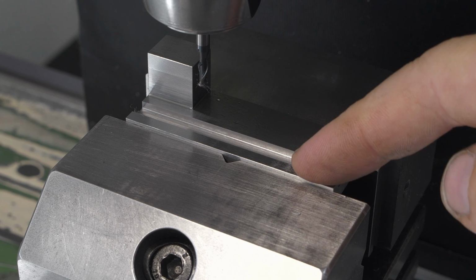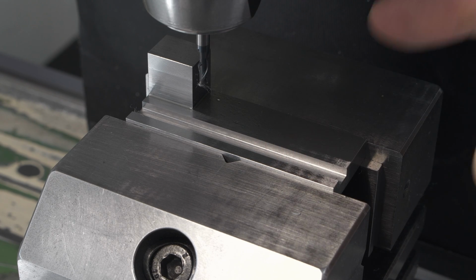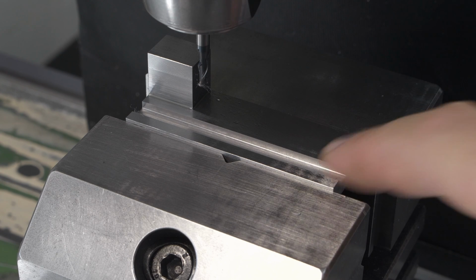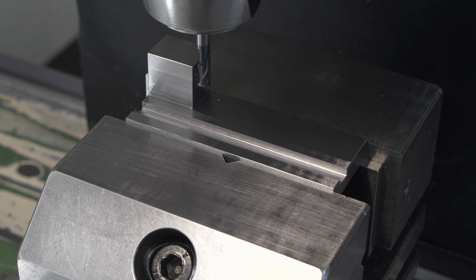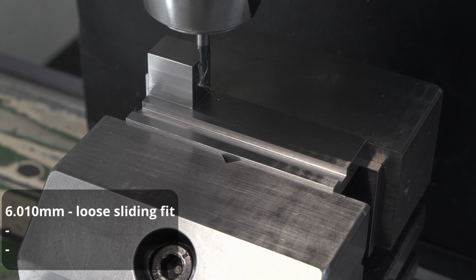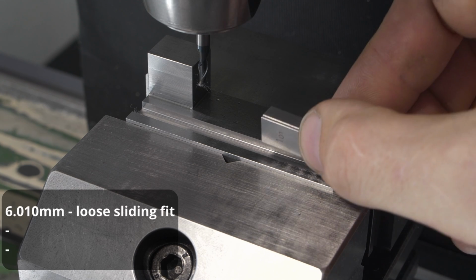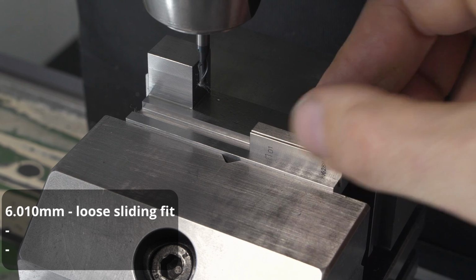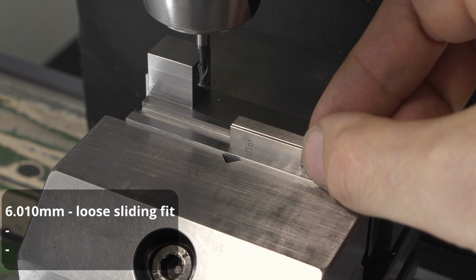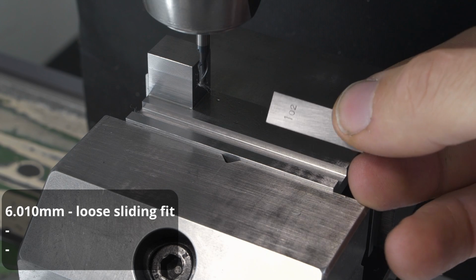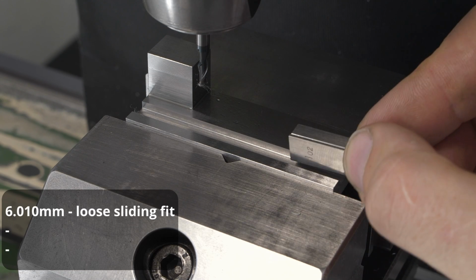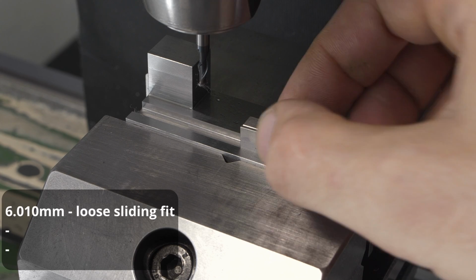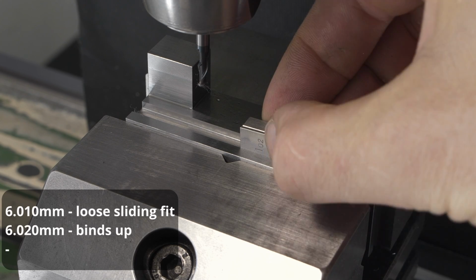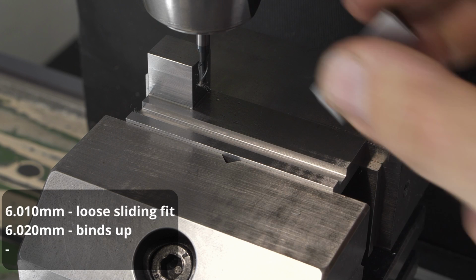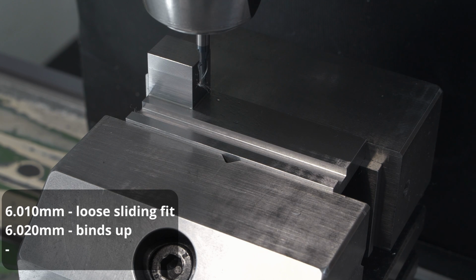I cut the slot in the part using a 4mm end mill, and I finished it to a size. So a 6.01mm gauge block with a nice loose sliding fit in there, and a 6.02mm gauge block stack. Wants to start, but gets tight immediately. So the slot is between 6.01 and 6.02 millimeters.